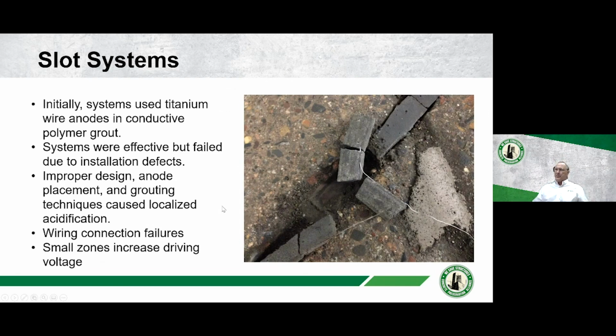So essentially, what they started out using was this titanium wire, and they put it into these slots and they poured the grout on top of it. Well, they didn't have great quality control, and the wire eventually found its way down to the bottom of the slot. It didn't get coated by the polymer, and it acidified the concrete, because when you break down water, acid is formed at the anode if this gets moist. And because it wasn't embedded in the grout, this is the kind of situation that will occur, and then the concrete breaks apart, and then the grout comes out of the slot. So that was basically an installation defect that they learned the hard way.